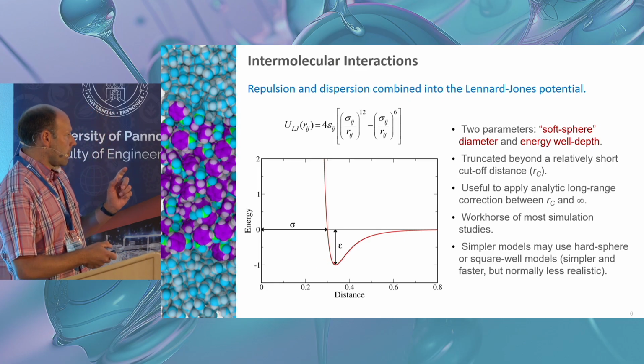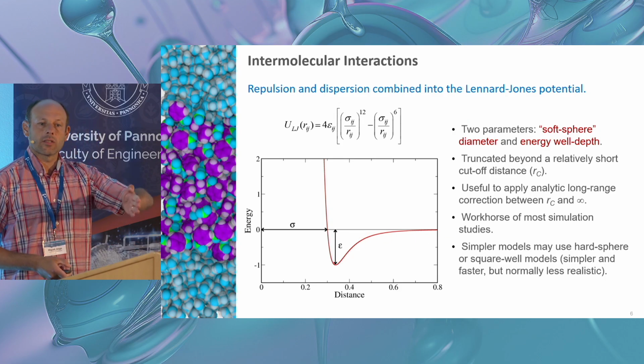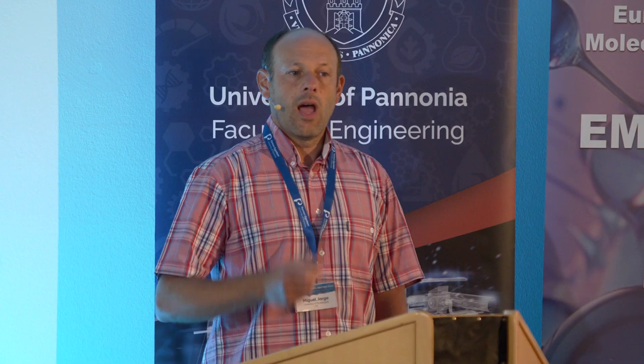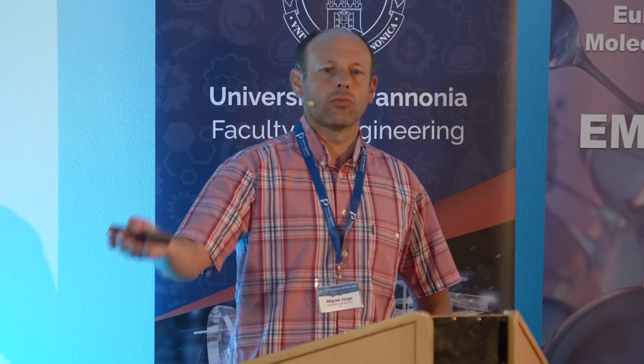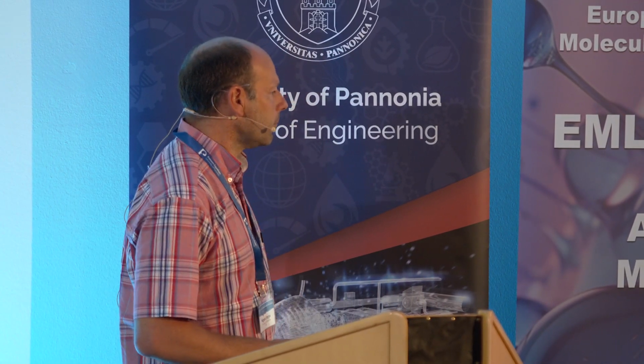So the other small thing to say here is that because this decays very fast with distance, we normally truncate this at a cutoff radius called the RC, right? So cutoff radius. After that, there are many different ways, but essentially we render the interaction down to 0, okay? And there's ways to compensate that using long-range corrections, which again, I don't really have time to talk about, okay?